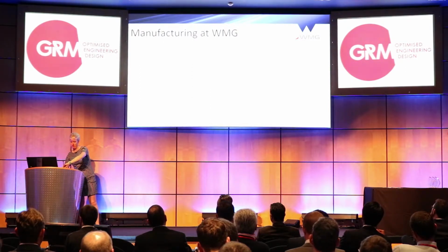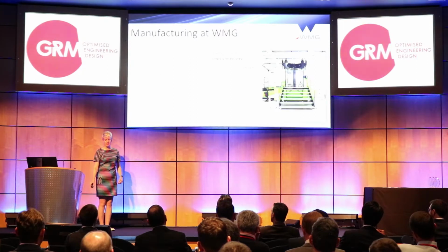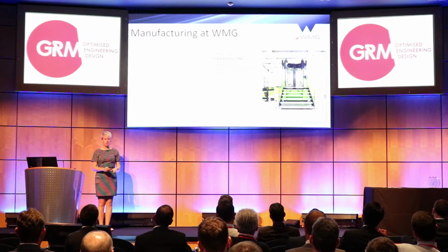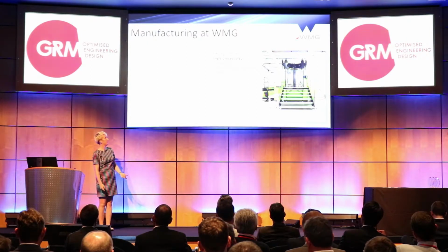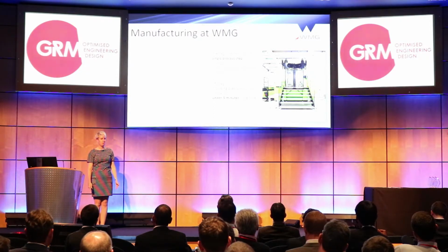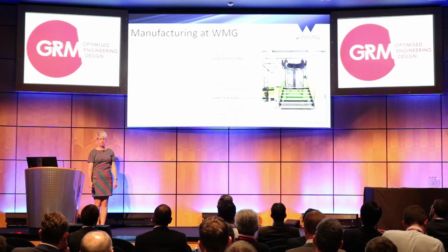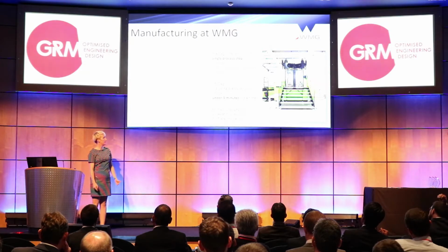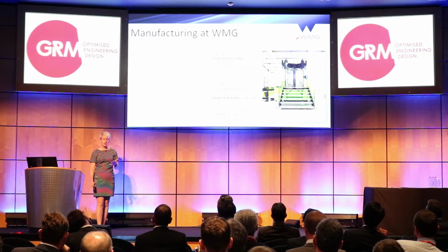So, manufacturing the compression mouldings, this was the big step that we knew we were going to be doing. We managed to compression mould the prepreg, steel and SMC in a single process step. We used off-the-shelf materials from Mitsubishi Rayon. We moulded at 150 degrees with pressures up to 100 bar, and this is where we did achieve the under 5 minute cycle time. Within the mould, there were 6 pressure sensors, 3 heat flux sensors and 2 dielectric sensors, which allowed us to monitor the flow of the material and the cure of the material in real time.